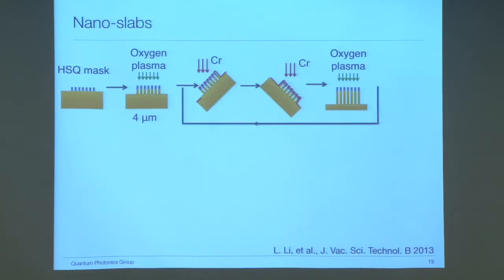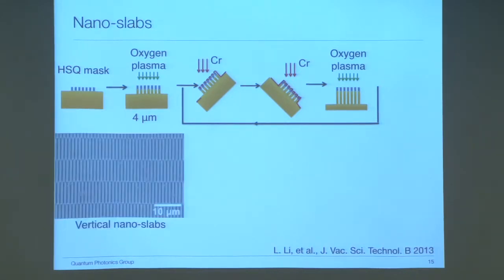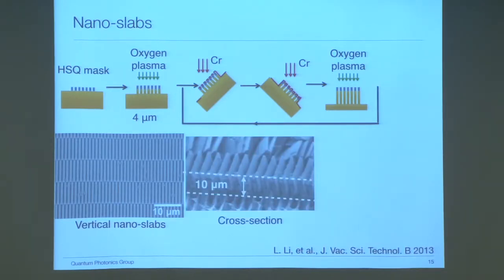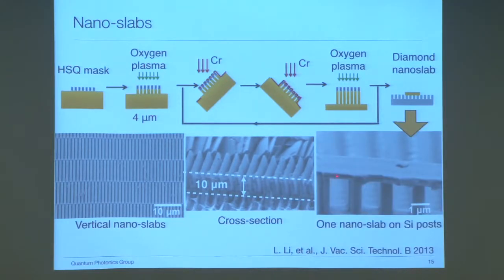By repeating these deposition and etching steps multiple times, we are able to produce vertical diamond nanoslabs. As you can see here, the top view of these vertical diamond nanoslabs, and also the side view of the cross-section gives us the height information. It's about 10 microns in height. And then we can break off these diamond membranes and transfer them onto another substrate. This SEM image is a diamond nanoslab on top of silicon standoff posts.